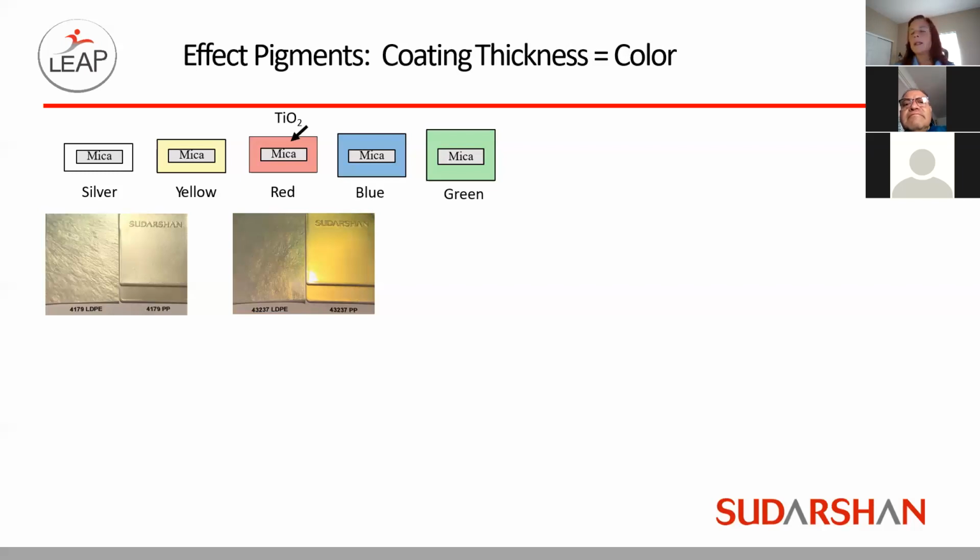And then on the right-hand side is an injection molded part chip that shows how much more evenly dispersed the micas are in terms of orientation. So the waviness is removed because all of the flakes are equally oriented in a flat position. So you start to see a little bit more of the sparkle and the luster that comes along with it.